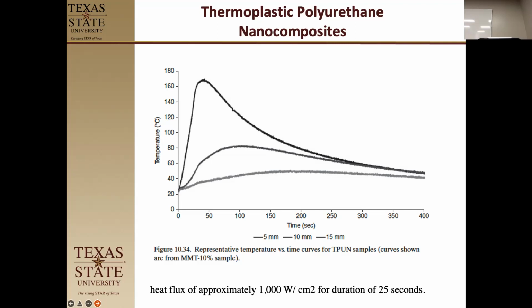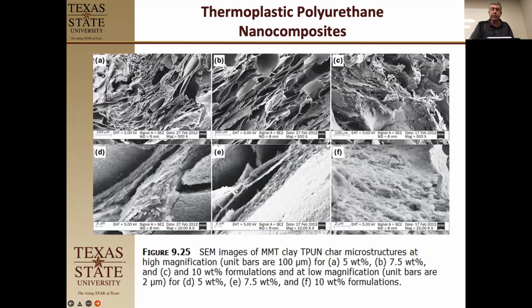So we're looking at it as a good thermal insulator, even with a high heat flux. We're seeing that it has very good, this is the 10% montmorillonite. This is the one that performed almost the best on the ablation testing as well. So they're showing that it has good thermal barrier properties as well as good ablation properties.